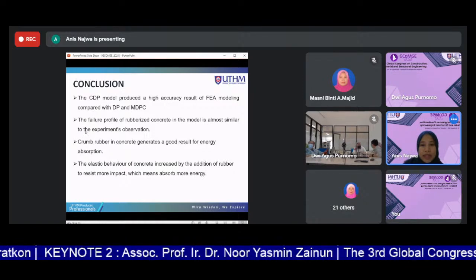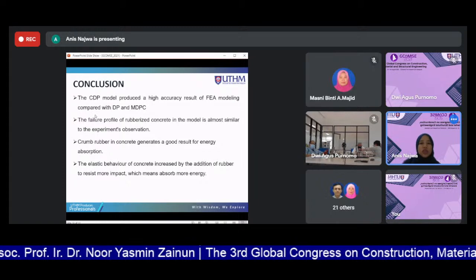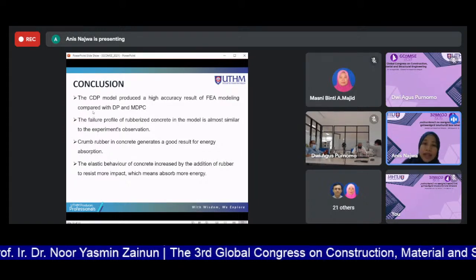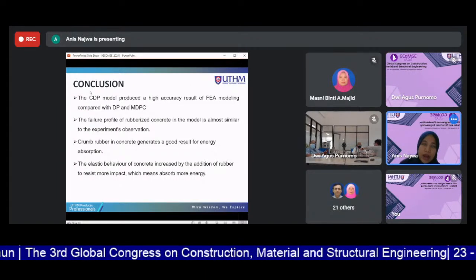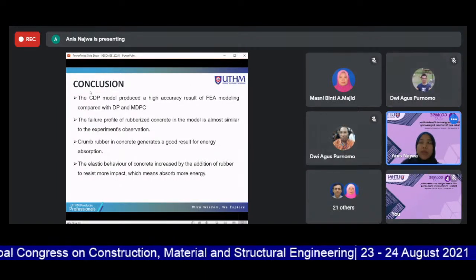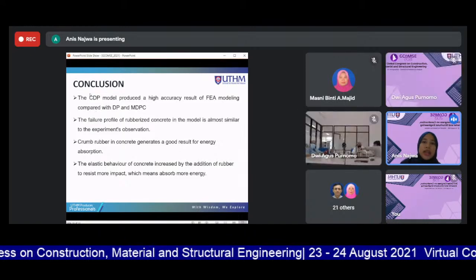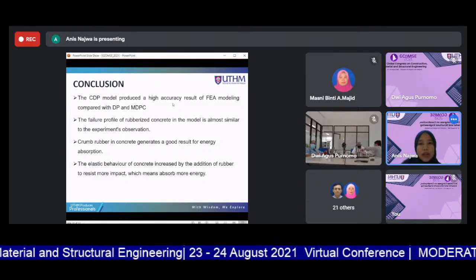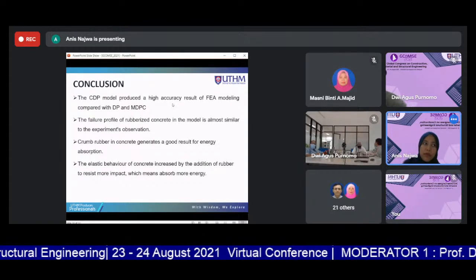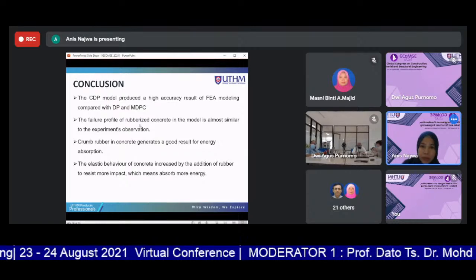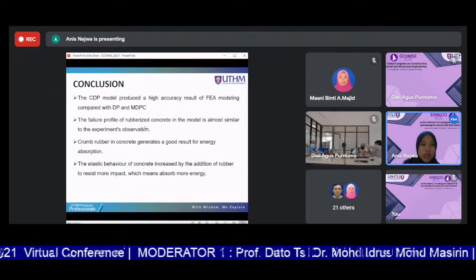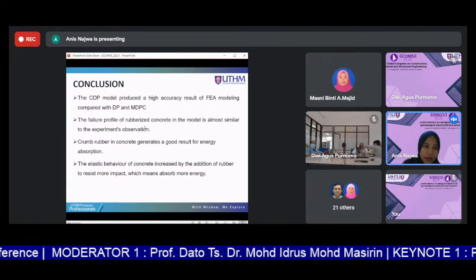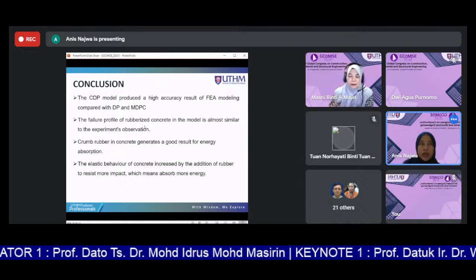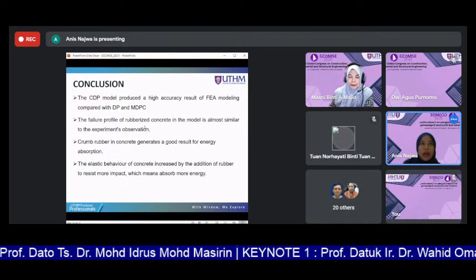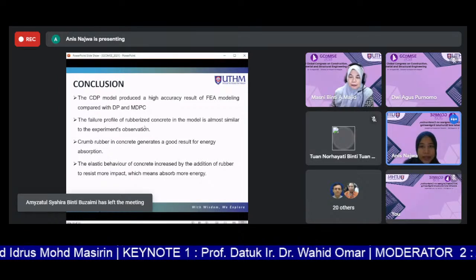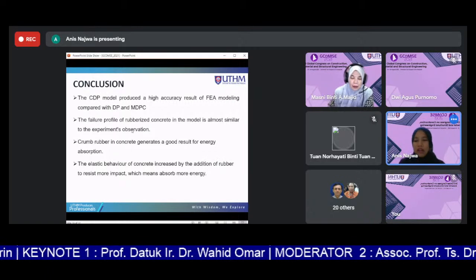which means absorbing more energy. So to highlight the conclusions here, to model the rubberized concrete, the concrete damage plasticity model is the more accurate one, or not to say accurate, but better. And the replacement with rubber actually helps a lot to give a good energy absorption result compared with normal concrete, which does not have rubber. So it can first help reduce the waste, the production of stockpiled tire waste. And second, it can give good energy absorption, which can reduce the impact and the damage to the vehicle during an accident. Okay, that's all from me. Thank you.